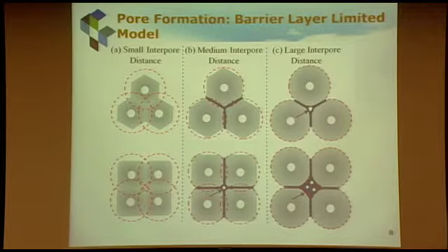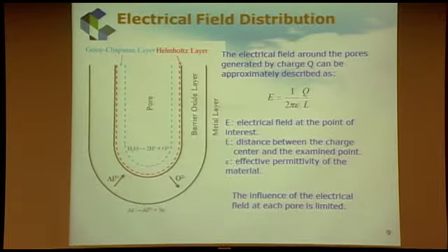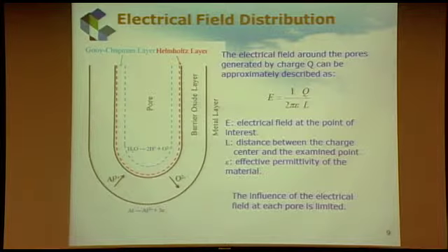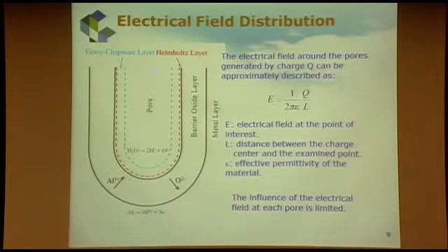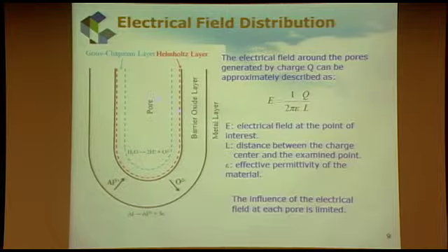So we figured all this out, and I might go a little bit faster on this, but these are the fundamental processes. Basically, for all the chemistry people, it's a no-brainer. You actually have several layers. This is your liquid, the acid, and this is the solid. So in this liquid process, you have this Gouy-Chapman layer, you have this Helmholtz layer, and then when you get into the oxide layer, it's a major region that carries your voltage drop.